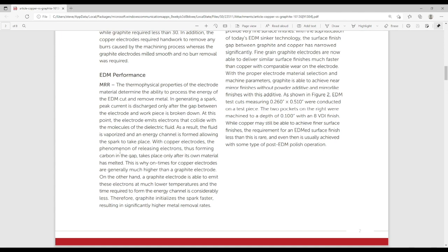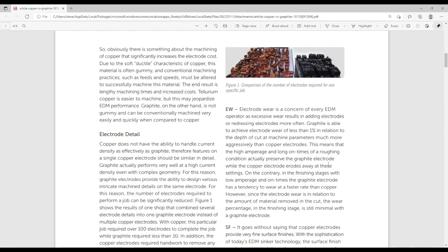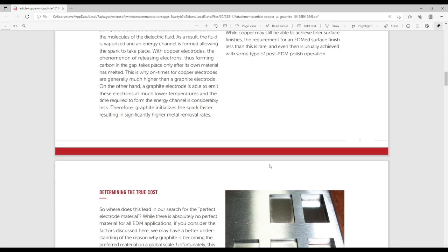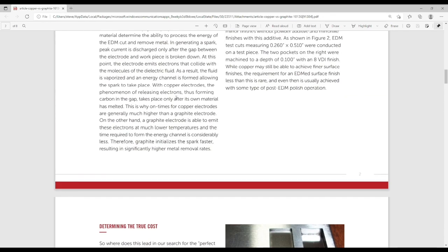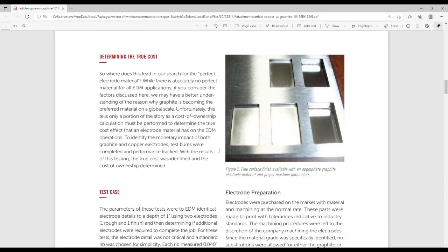With copper electrodes, the phenomenon of releasing electrons, thus forming carbon in the gap, takes place only after its own material has melted. This is why on times for copper electrodes are generally much higher than graphite electrodes. On the other hand, the graphite electrode is able to emit these electrons at much lower temperatures, and the time required to form the energy channel is considerably less. Therefore, graphite initializes the spark faster, resulting in significantly higher metal removal rates. That is the technical end of it. So basically, you can flow more current through your carbon or graphite electrode versus the copper, which I thought was reversed. So I'm learning as we go here as well.